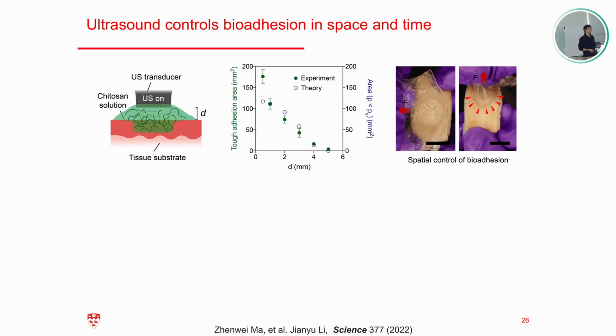So what's the benefit of that? The ultrasound has a super localized effect. So the first proposal here is that we can use the ultrasound to control where we want the adhesion to form. Before that, we studied the localized effect of ultrasound. We control the distance between the ultrasonic probe and the substrate, and then we characterize the area of the adhesion that can form under different distances.